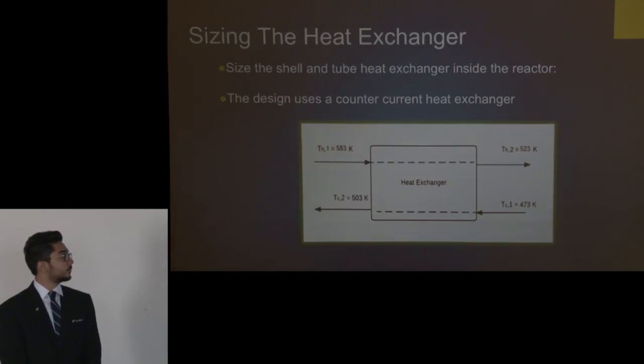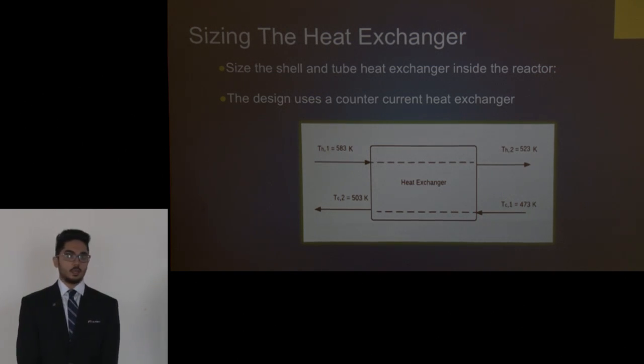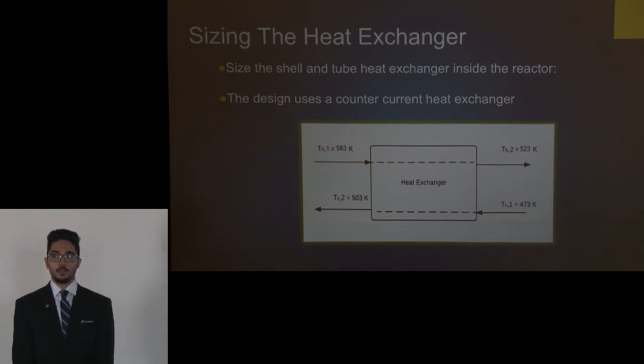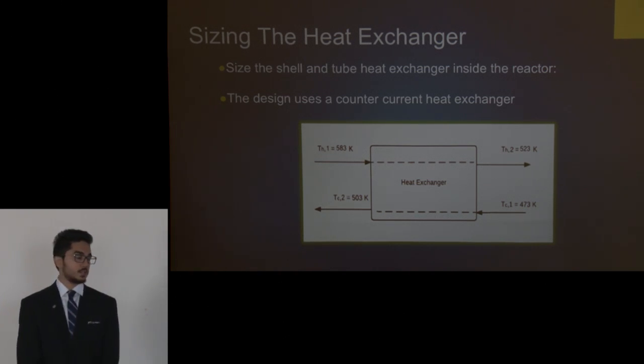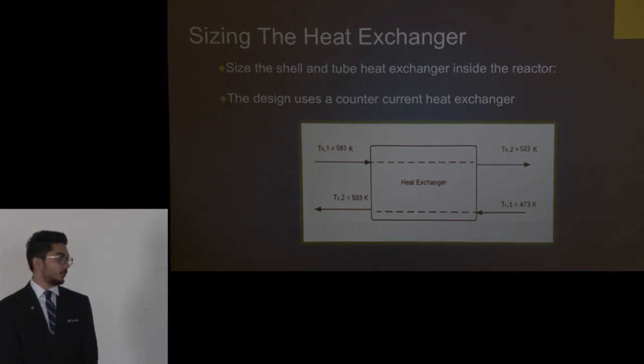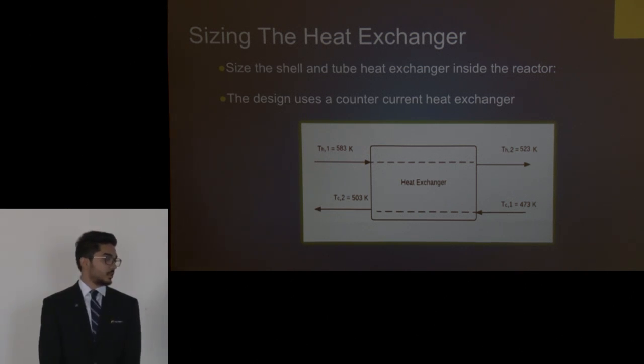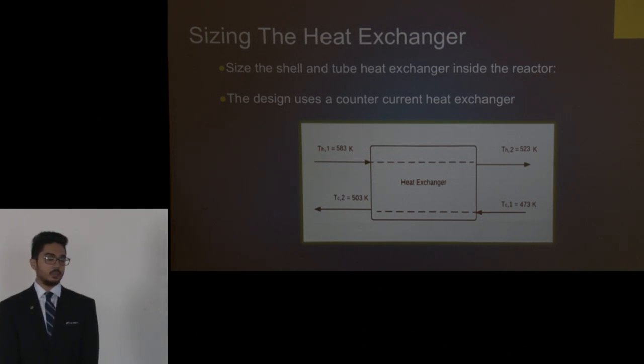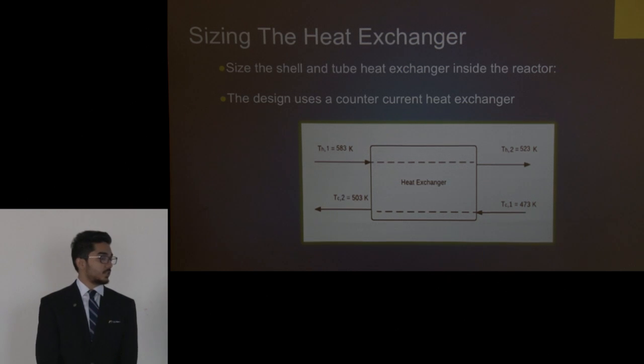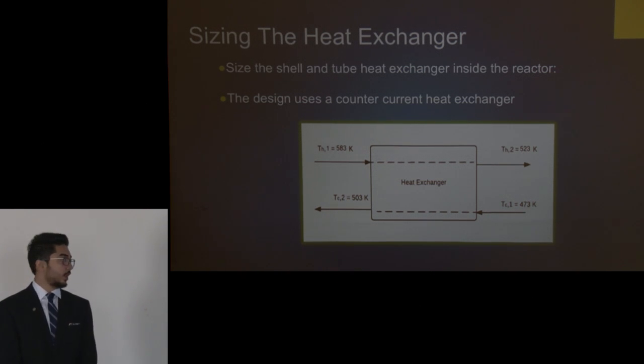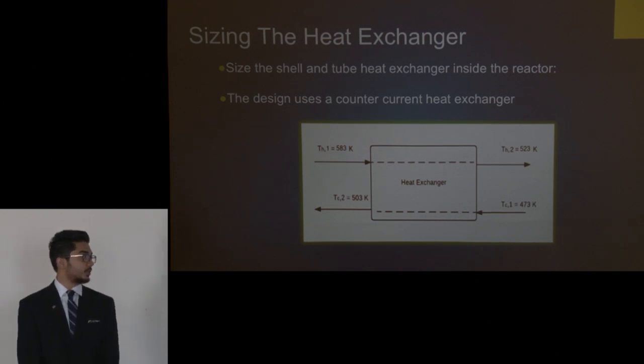bed reactor. So according to our kinetics, the reaction rate would decrease rapidly when operating at temperatures lower than 250 degrees Celsius, and temperatures higher than 330 degrees Celsius will alter the composition of our catalyst, causing some of the substances inside the catalyst to evaporate. Therefore, the temperature must be maintained between 250 and 330 degrees Celsius. That's why we integrated a heat exchanging system inside our reactor, which is a shell and tube heat exchanger with a counter current flow.